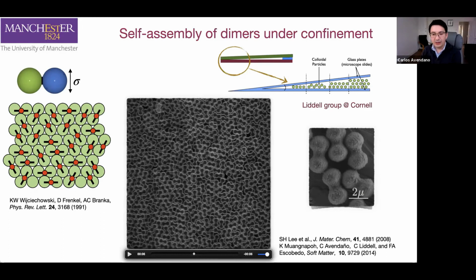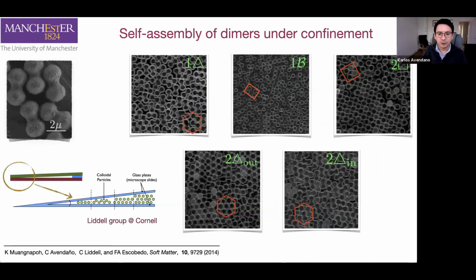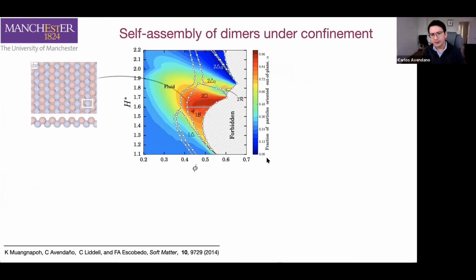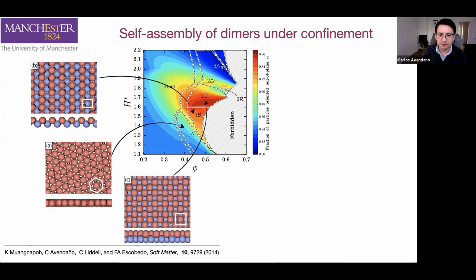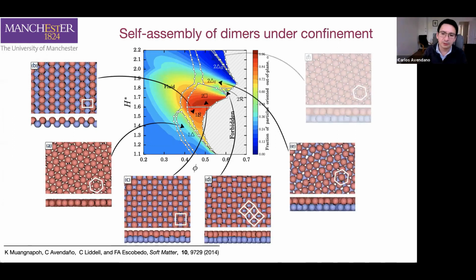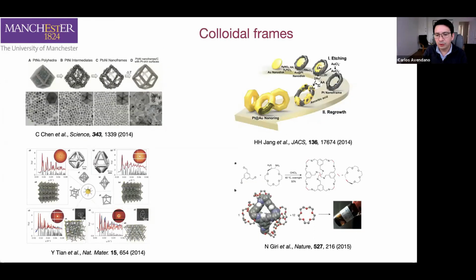experiments. But now, using similar simulation techniques as the one I explained before, we managed to also reproduce the entire phase diagram observed in experiments for different heights. So formation of monolayers and bilayers. And this is the type of phase diagrams that we observe. So again, this is just to show you how with Monte Carlo simulations, we were able to represent the experimental observations quite well. But now coming to more anisotropic or more non-convex particles, one that I'm particularly interested in is